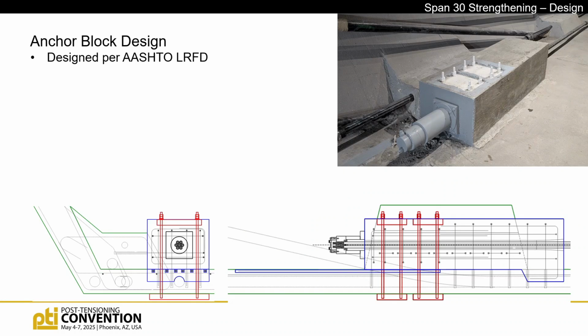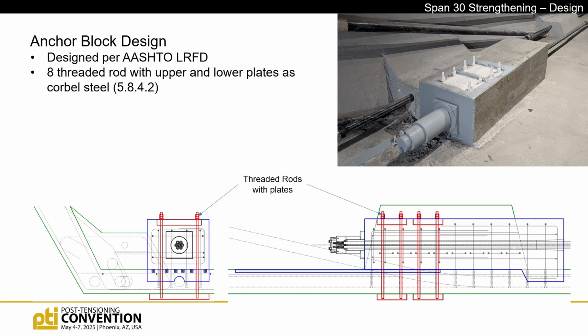Now, only tendon B required an intermediate anchor block. So that's what that one looked like here. The other ones we cored through the diaphragm. We'll see those in just a minute. So this is what the new anchor blocks look like. We designed it, of course, per LRFD, but we used 8 threaded rods that had upper and lower plates to act as corbel steel. Now, they were immediately developed on the bottom side by using drilled and tapped holes in the partial depth, drilled and tapped holes in the lower plate that is outside the bridge on the bottom slab.